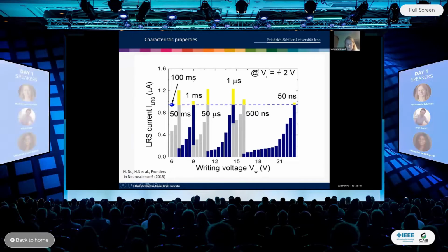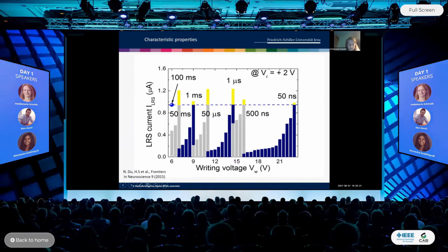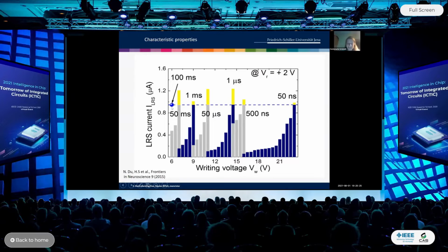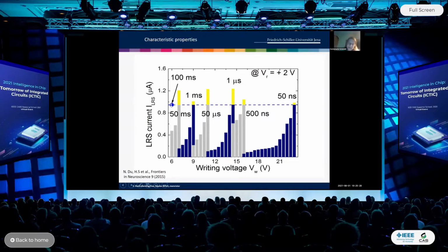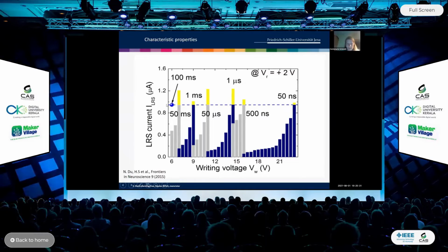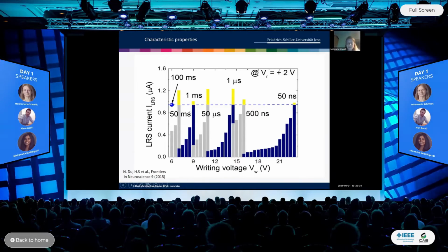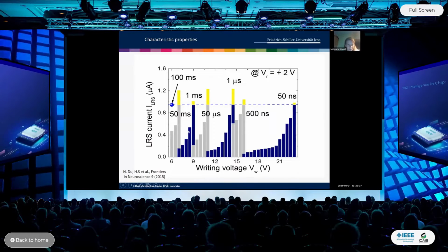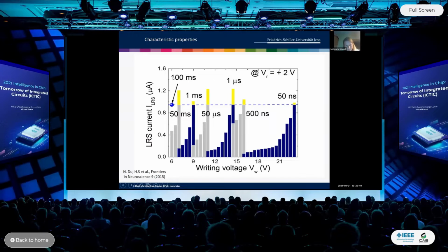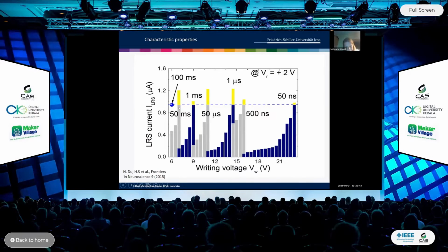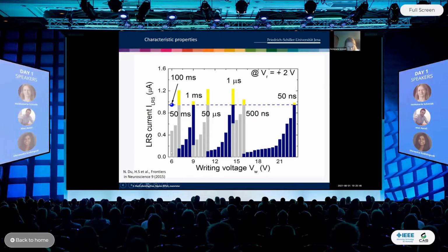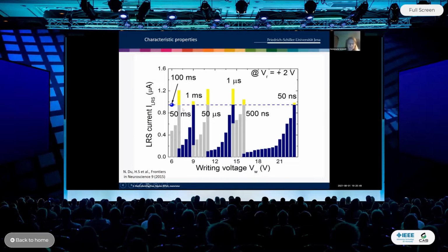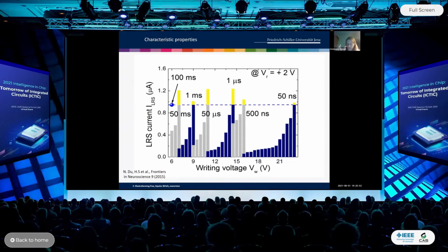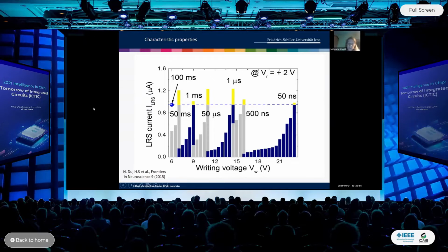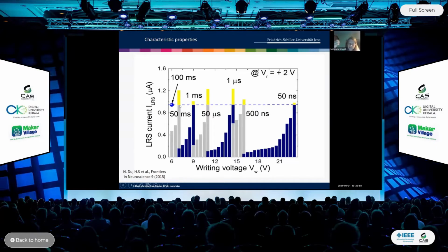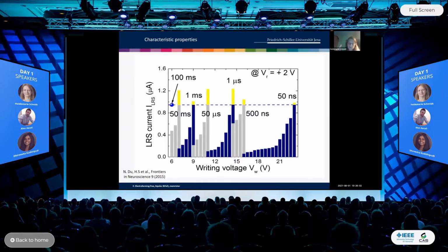Okay, we started with the 100 millisecond long pulse with an amplitude of 6 volt. This is the standard writing procedure we apply, and then we know it can be switched from high to low resistance state. And this current level we took as a reference. Then if we reduced the width of this writing bias from 100 millisecond to 50 millisecond, we had to apply a writing voltage amplitude of 6, 7, 8 volt. Only with a shorter bias and a larger amplitude could we drift enough oxygen vacancies from the top to the bottom electrode.